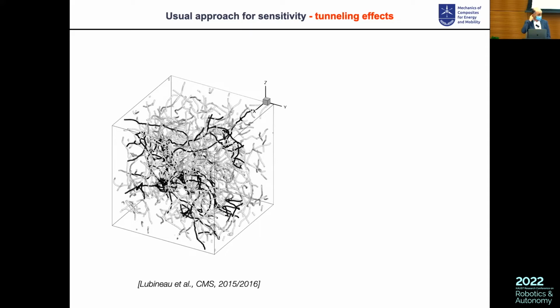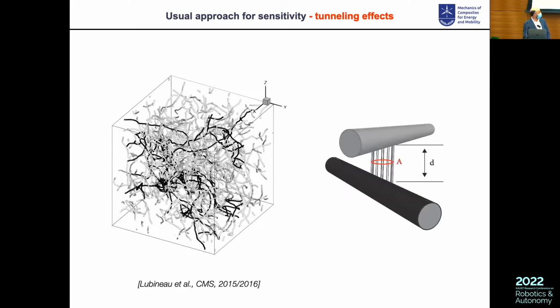There are different, very classical approaches to do this. The first one is to take a cloud of conductive nanoparticles. You take a polymer, something that is insulating, and you put inside a cloud of wires that are conductive, right? When you put in enough particles, you get what you call percolation. You have a percolated network, the black network here, that is going to conduct your electrical signal. And the conduction is mainly dependent on the interaction between the particles.